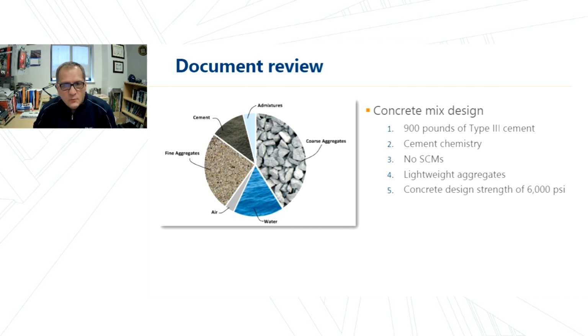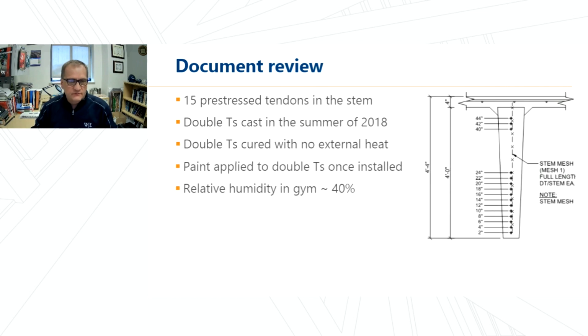In addition, we found that the chemistry of the cement was the right chemistry for DEF to occur, which we subsequently verified in the laboratory. We also found that no supplementary cementitious materials, SCMs, were used. And this is important because we can include SCMs that will actually help mitigate DEF. We also found that the coarse aggregate was lightweight, and we'll circle back to why that is important a little bit later. And we found the design strength of 6,000 PSI. So useful information from the document review.